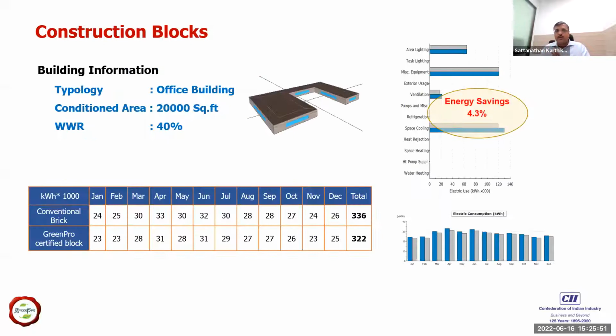I will just show you some results, how things are working. For example, we have done a simulation of a building made with a red brick wall, and also a similar building made with AAC block. When you do the simulation for the whole year, a building made with AAC block has an energy consumption about 4 to 5% lower compared to a building made with a red brick. The 4 to 5% may look like a very small number, friends, but this is over the lifetime of the building. You are able to bring down the energy consumption by about 4.3%.